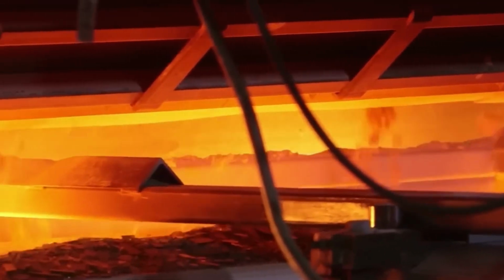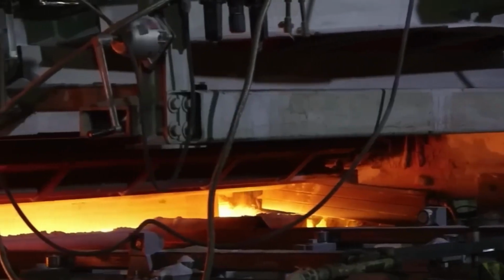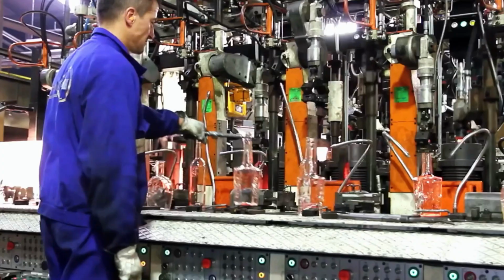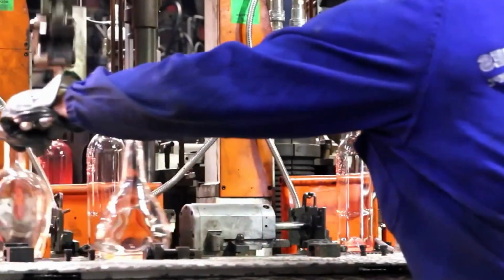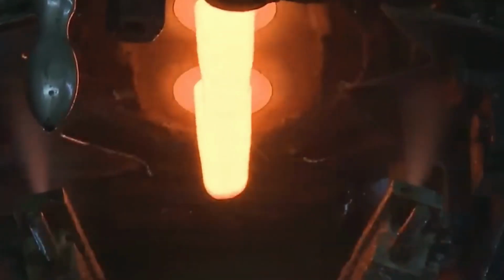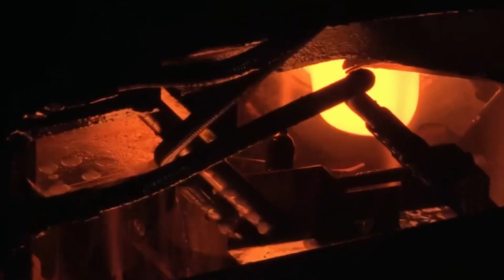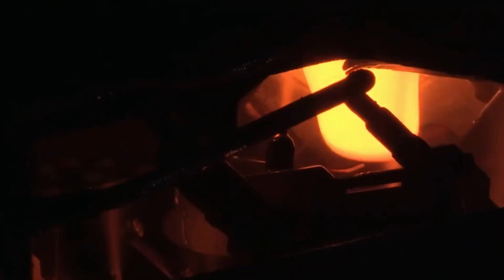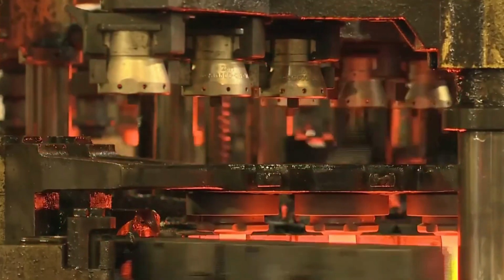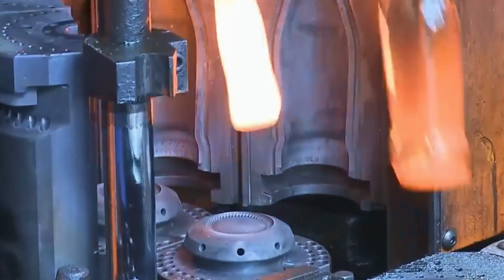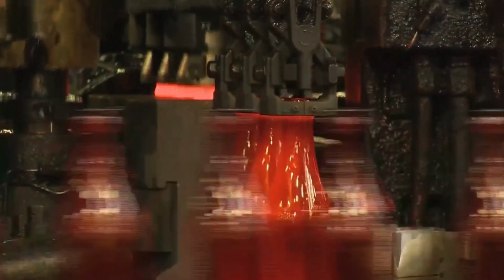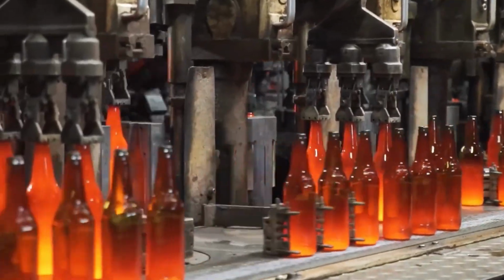Here's what happens if they lose control. If temperature drifts by 10 degrees, crystalline stones form, hard mineral shards that freeze inside the melt and burst bottles under pressure. Stones are invisible in the melt, but catastrophic in the bottle. A single stone can cause a bottle to shatter during filling or transport. Regenerative burners recover up to 60% of exhaust heat. That cuts fuel consumption by 25% compared to conventional furnaces. This is the invisible system that keeps the glass from literally exploding.